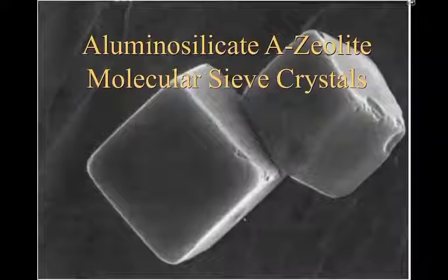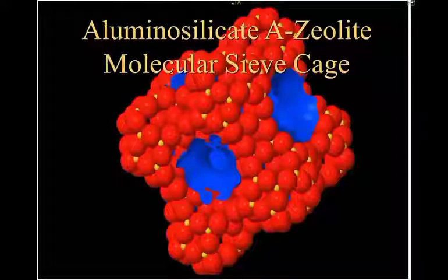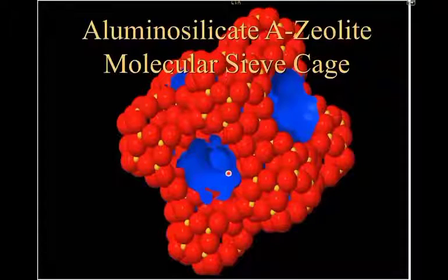So there'll be about 3,000 to 4,000 pinholes in every single dimension on the surface of this crystal that would look something like this. This is sort of the atomic view. You can see the tiny little opening here in the center. That's about 5 angstroms for this particular structure. In the X-type zeolite, that may be 7 or 8 angstroms.